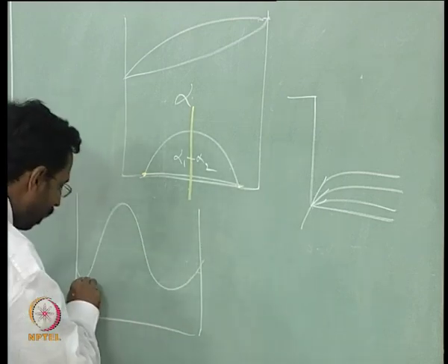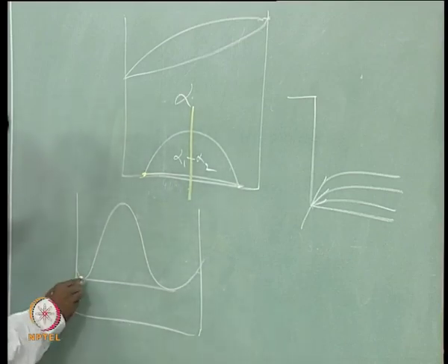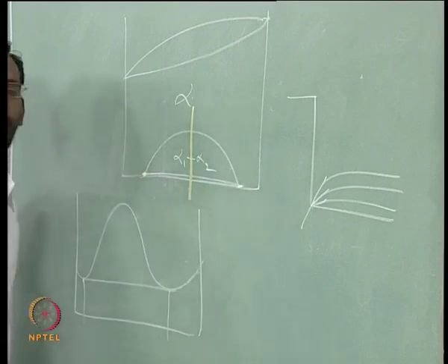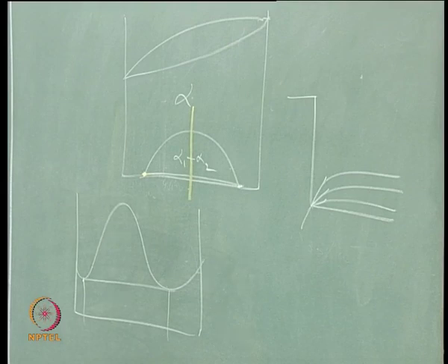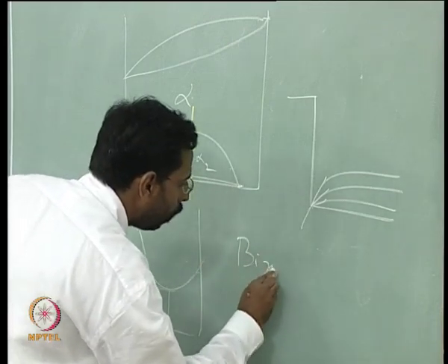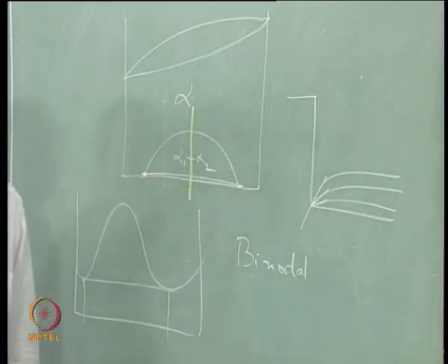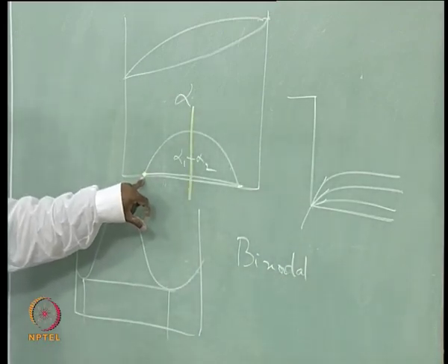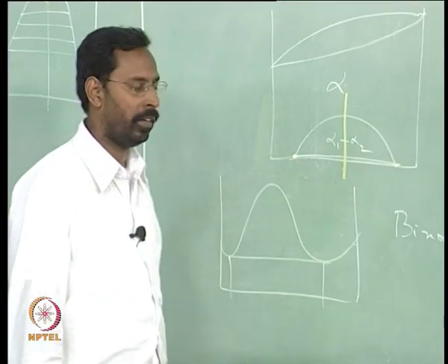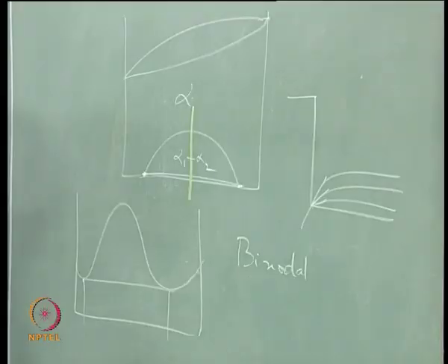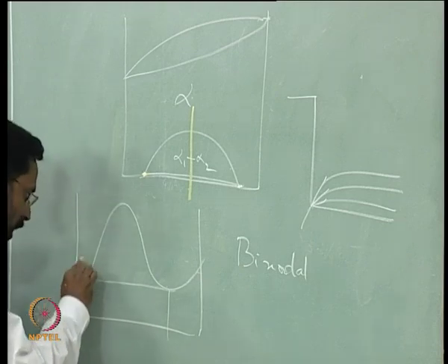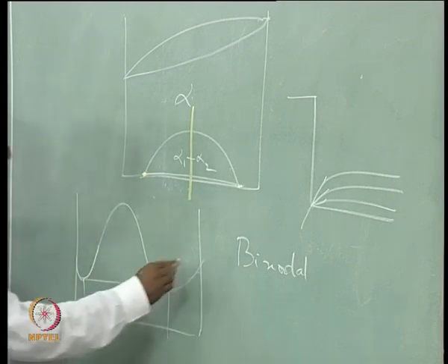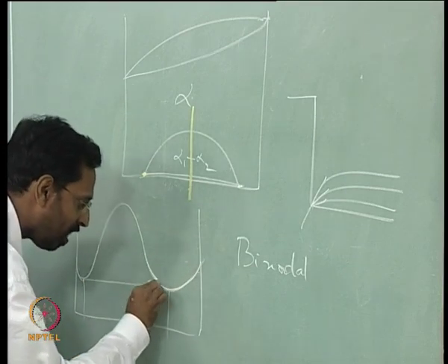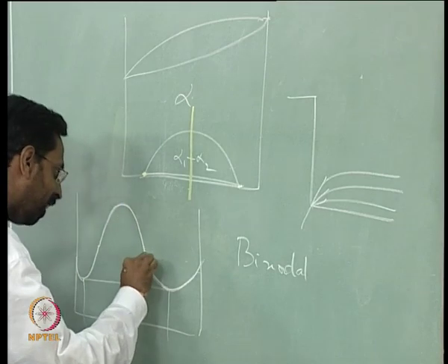And if that is the case, if I draw a common tangent, you get these 2 points, and what are these 2 points? We call them the binodal points. They are usually called the binodal points. They are nothing but the equilibrium compositions of alpha 1 and alpha 2 at that temperature. Now, if you look at this, this particular free energy curve appears to be a mixture of 2 types of free energy curve, one which is a curve like this, another curve which is like this.